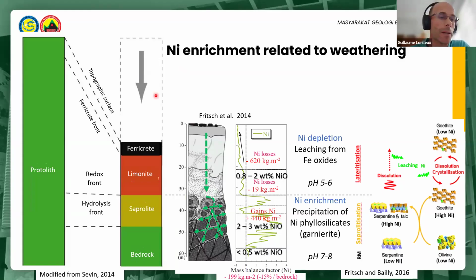So as you can see on the left figure, considering that 1 meter of limonite results from the weathering of 6 meters of peridotite, and considering a dry density of 2.7 grams per cubic centimeter in bedrock and 1.1 gram per cubic centimeter in limonite, 0.3% nickel in bedrock would be converted into 4.4% nickel in limonite. However, as we know, nickel grades in limonite are generally less than 2% nickel, suggesting that some nickel has been leached.